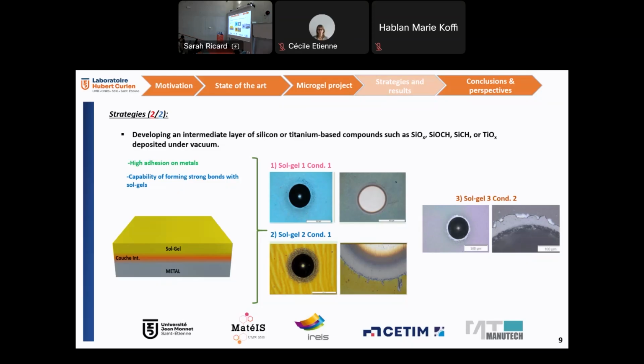When you are using this strategy in the different conditions, such as sol 1, condition 1, you can see good results for this Rockwell indentation. You can see a well-defined calotest. In the sol-gel 2, condition 1, a little bit of radial fissure close to the area, but you can see homogeneity and continuity in the sol. And here you can see the normal radial damage for this kind of experiment, and a good result for sol 3, condition 2, again, as you can check.